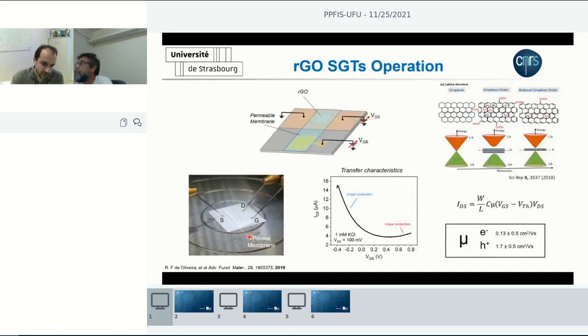So here is a picture of our device under measurement. We confine the electrolyte using a porous membrane sitting on top of both source and drain and gate. And here's the typical curve of reduced graphene oxide, which is supposed to be ambipolar.